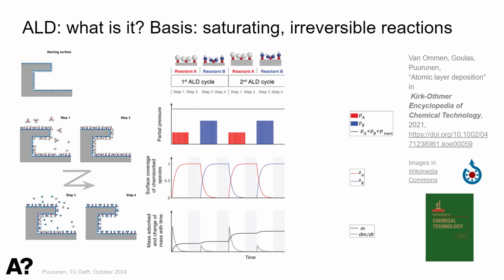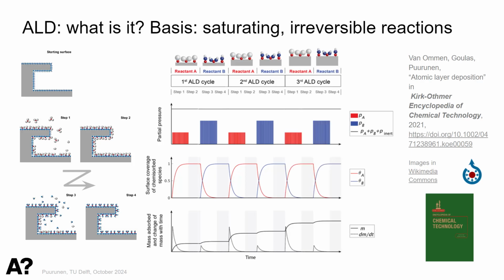And these cycles you then repeat, they look exactly the same, except that there can be some surface effects, and the layer grows this way. And this process is exactly the same, whether you are talking about catalysts and particles or planar wafers. And sometimes you just do one cycle or a few cycles or thousands of cycles.